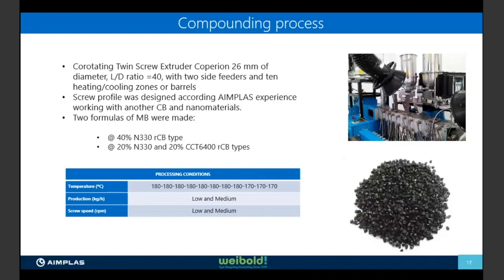When we tune the different mixing energy, you know that mixing energy is very important when you try to disperse very complicated substances like carbon black. With low and medium production and screw speed, you can have different specific mechanical energy, which is related with shear and also with dispersion. And that's what we obtained.